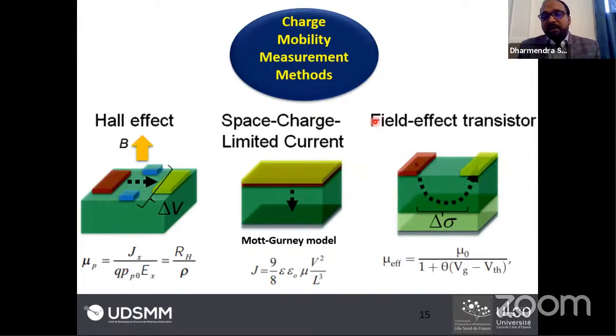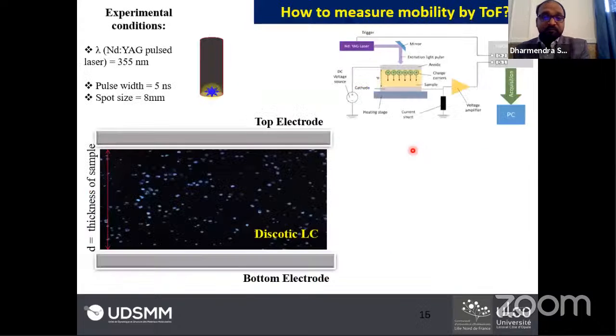So basically here we are dealing with electronic, electro-optical, and photonic properties in our laboratory. We are experts in charge carrier mobility measurements in organic devices. As you know, you can measure the charge carrier mobility via the Hall effect in inorganics. You can also measure the mobility with the space charge limited current method, that is the Gurney model. And nowadays people are also measuring the mobility using a field effect transistor. But here we are specialized in measuring the charge carrier mobility using the time of flight setup.